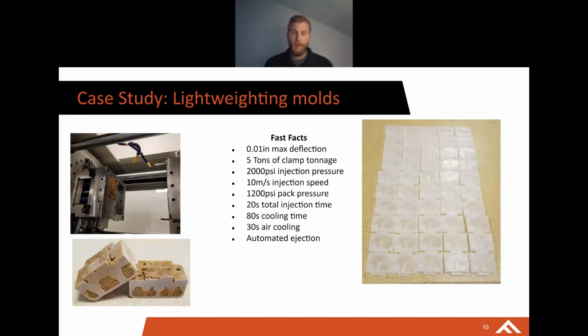While we're heating that barrel really hot and taking a really long cooling time, one of the first things we get asked about is mechanical properties. One of the ways we combat material degradation is to put in either a charge delay or plasticizing delay, depending on which press you have. The vernacular can be a little bit different. But what I'll do is run with an extremely low cushion, something in the 1/8 of an inch or a couple millimeters, in order to have as little material in the barrel sitting there heating up. And then I'll put like an 80-second or the full cooling time. So instead of having my plasticizing take up 70 to 80%, like in traditional molding, I'll have it take 0%.